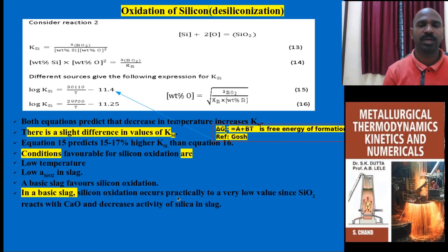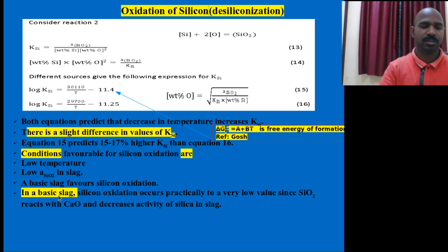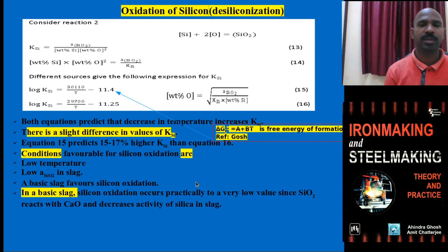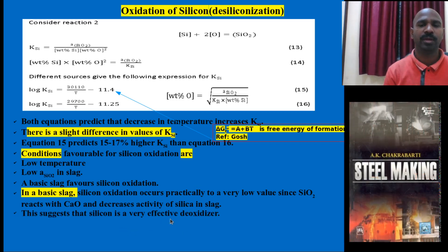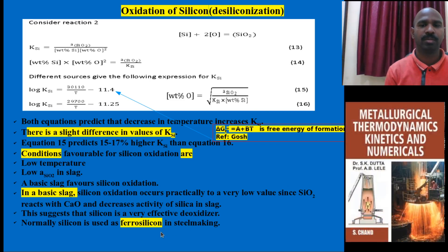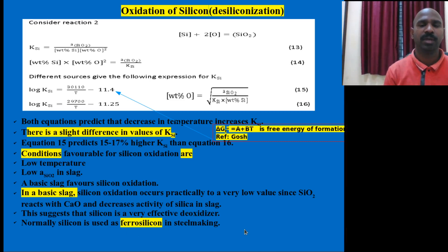In basic slag, SiO2 reacts with CaO of the basic slag and decreases the activity of silica. Combining with the basic slag, silicon will go out and the amount of silicon retained in the steel after the secondary steelmaking refining process becomes low. Silicon is also an effective deoxidizer. If necessary, silicon can be added for few applications for improving machining utility and physical properties, in the form of ferrosilicon, during the secondary steelmaking process.